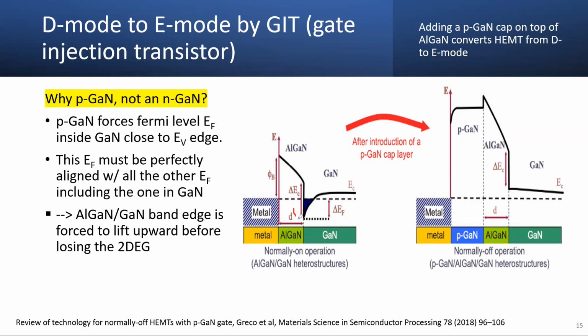The reason you have this normally on is because of the Fermi level. See the band bending; it occurs naturally inside a HEMT. The HEMT is normally on, and this is why the 2D gas is formed by nature. We have a full video describing why this happens. In one word, because AlGaN is strained, it forms a specific dipole.